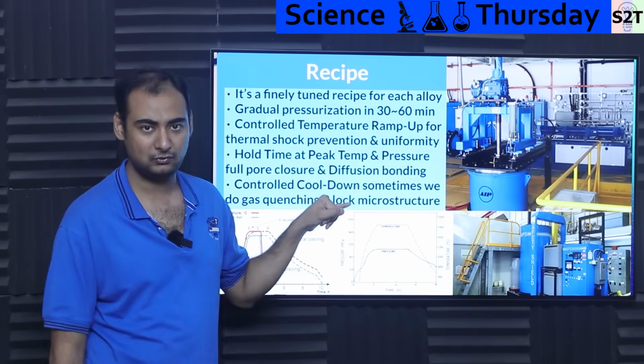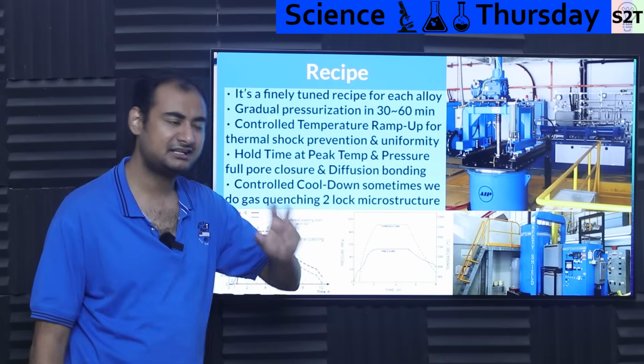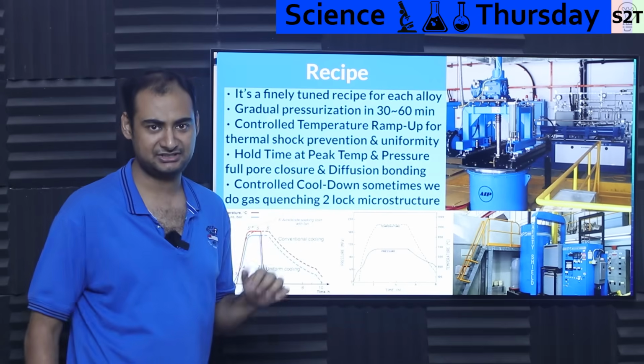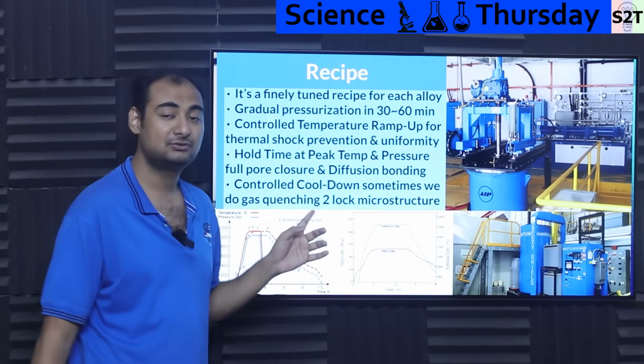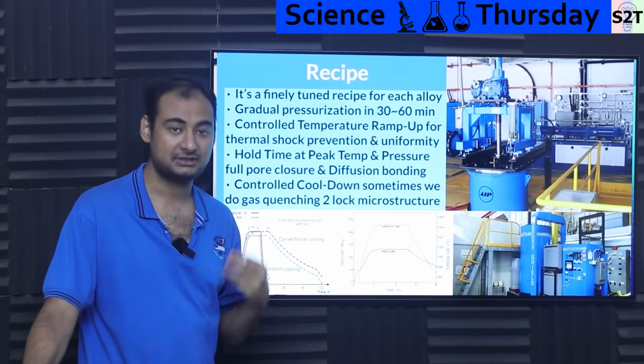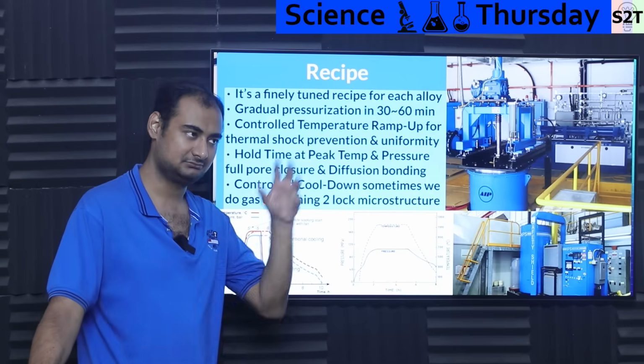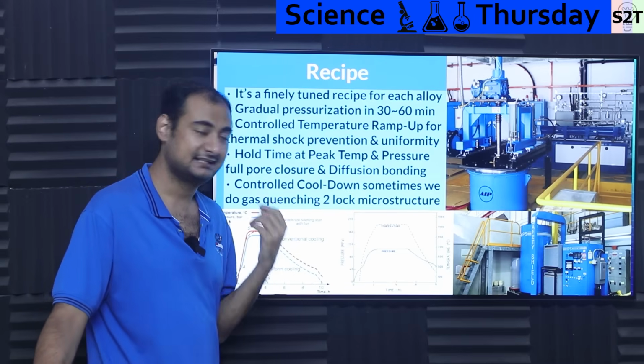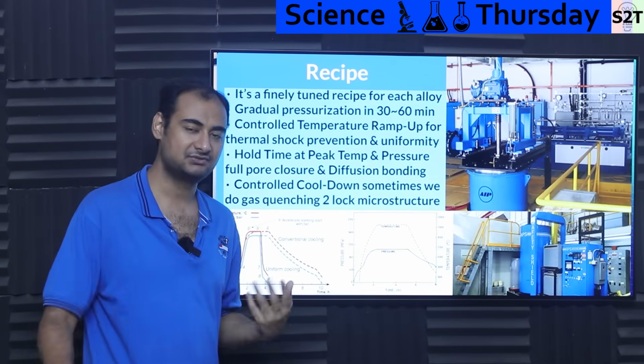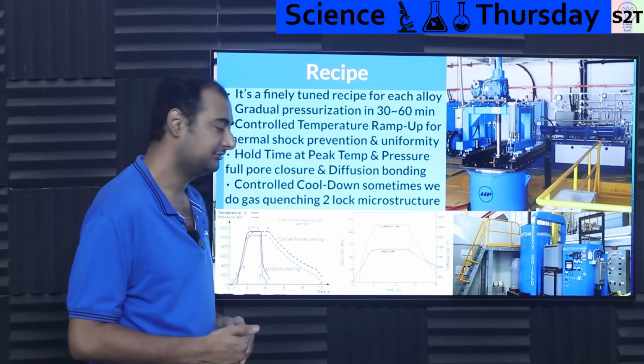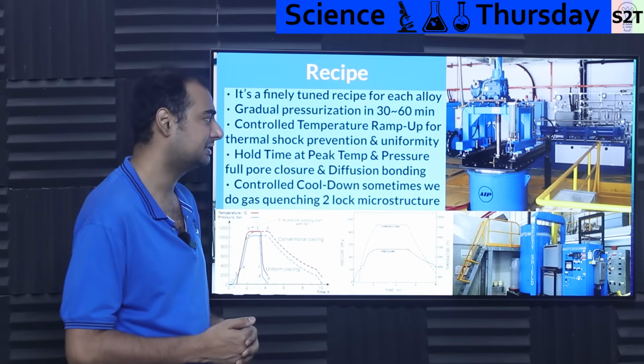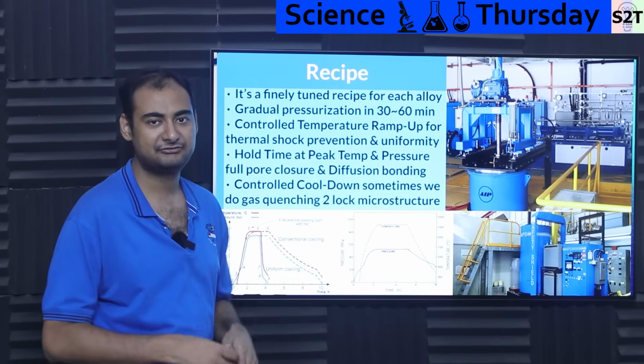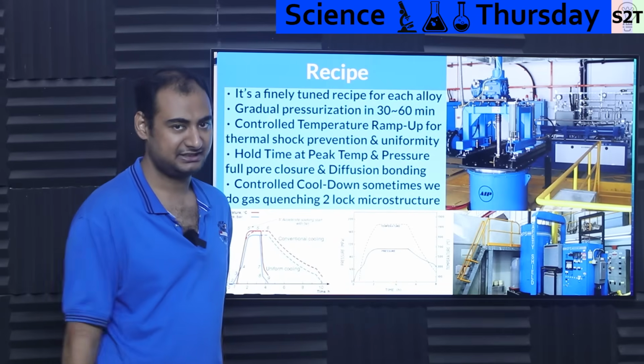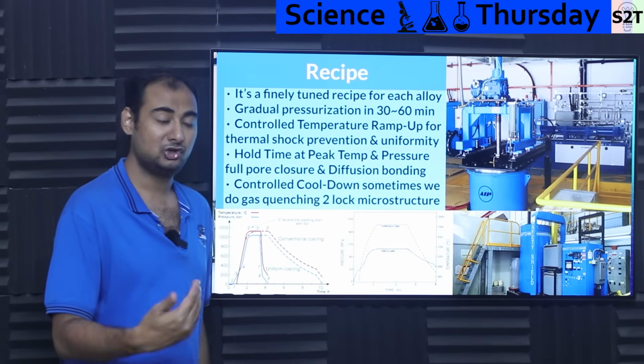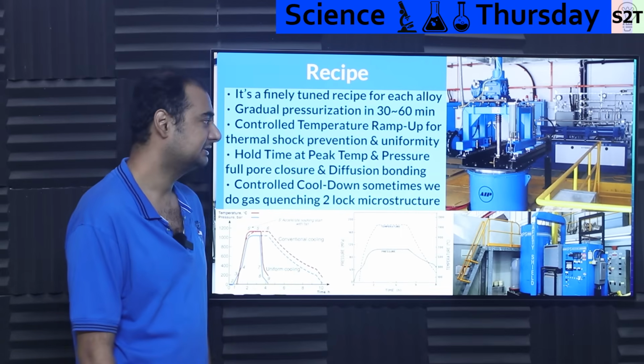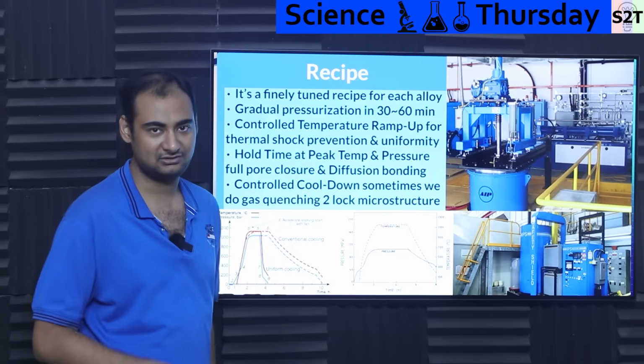And then you have controlled cool down. Generally, you will have normal cool down, but certain alloys require gas quenching. Gas quenching would be required if you want to lock in a microstructure. Certain alloys create certain unique alloy structures, and it's like, now we need to protect that. That gives you certain properties that you are looking for. You're like, okay, we're gonna do gas quenching, but that's rare. Let that be clear. Not every machine has that, and this has to be done for every alloy that you send into it. Ceramic alloys will have a different one. Aluminum alloys will have a different one. Platinum will have a different one. But somebody has to sit down and calculate all of these things.